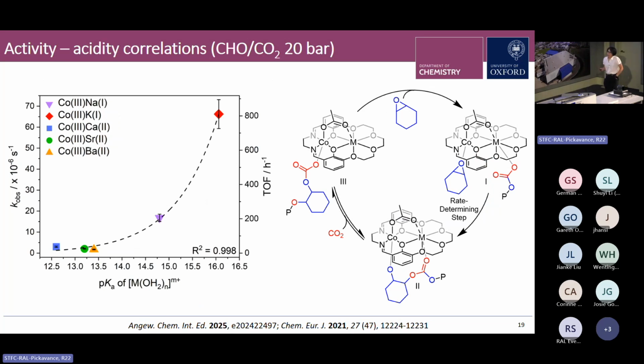now the rate determining step involves ring opening of a cobalt-bound epoxide via a metal carbonate nucleophile that produces this alkoxide intermediate, which can undergo rapid and reversible CO2 insertion to reform the carbonate. So if we consider our rate determining step and our key rate determining intermediate, which is this carbonate species, the least Lewis acidic S-block metals, sodium and potassium, are most effective because they most effectively labilize that metal carbonate bond, activating it towards ring opening of the epoxide, which increases your catalytic activity.